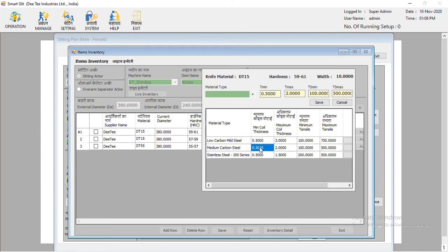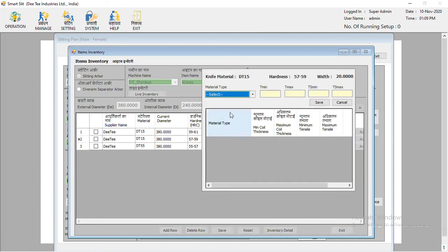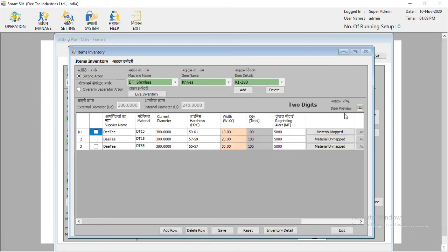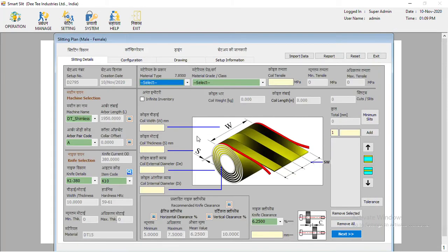Then on medium carbon steel I can use 0.5 to 2 mm, and similarly for stainless steel 0.5 to 1.5 mm, and this is the tensile strength range. So this is the mapping of knife to application. This is called knife application mapping, and this type of mapping we have not provided for 20 and 30 mm. So what is its effect on this particular screen, let us see.